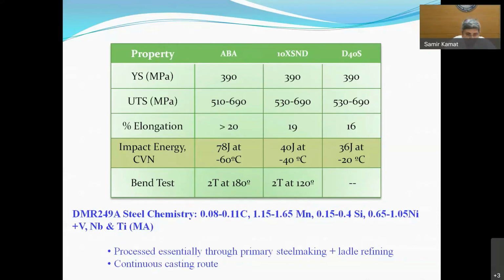So DMRL took up this challenge. They first made the steel within the laboratory at about 80 kg scale, which is the kind of furnace which is available within DMRL for steel making, and established that we could achieve the properties of the steel at lab scale. But you can imagine the next challenge is to scale up directly from 80 kg to about 80 tons, because the country does not have an intermediate capacity. So there is no intermediate capacity where you can try out making it at, say, 2 ton or 5 ton capacity. Directly from 80 kg, one has to scale up to 80 tons.